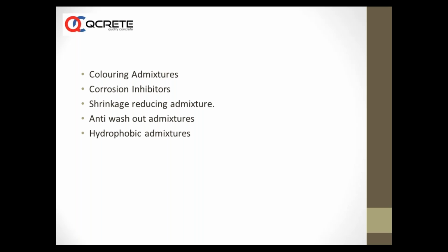Then we talk about corrosion inhibitors. Corrosion inhibitors are nowadays becoming very popular as the performance of concrete mixes is becoming the primary criterion and not the strength actually. You know, when oxygen enters into an RCC structure along with water, it attacks the reinforcement bar and the reinforcement grows in size after corrosion up to 6 times its original volume. So the corrosion leads to cracks in the body of concrete, deterioration of concrete, spalling, and it pushes the concrete to be almost the case where the concrete structures have to be demolished or they fall off on their own.